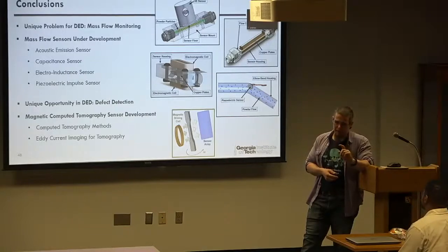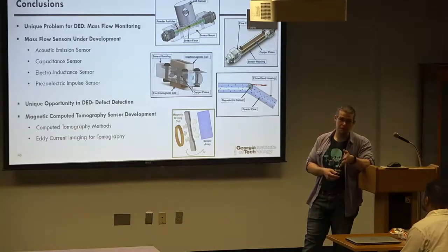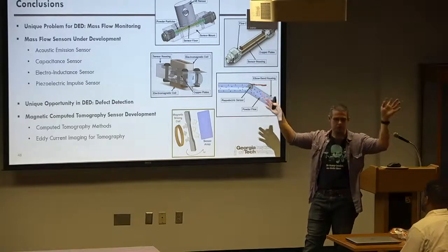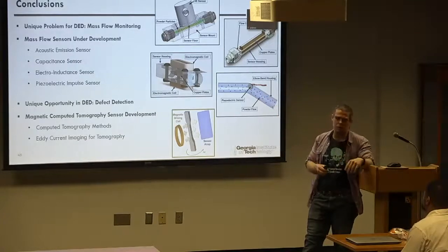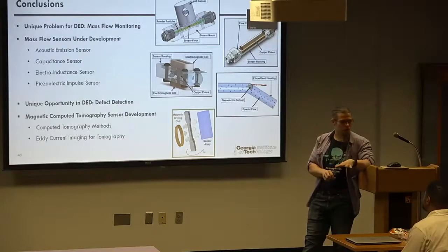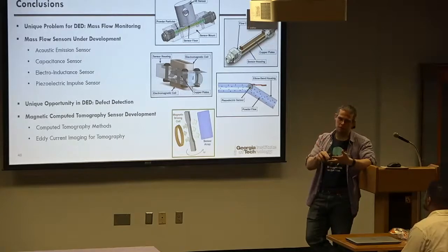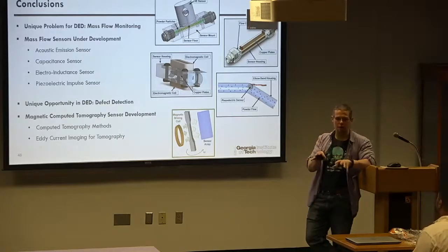And that's because as you print, you're introducing energy. Different materials evaporate at different temperatures, they have different vapor pressures and everything. So for example, if I want titanium with 6% aluminum, 4% vanadium in a final part, and you start with source material that is 7% aluminum, that's because that much of it just goes out into nowhere. It evaporates away and deposits somewhere on the inside of the machine. So it's going to be a combination of the feedstock that's being dropped in and all of the thermography data we can collect: the temperature of the melt pool, how big it is, how long it stays that hot. All of that information would have to be coupled with it too.